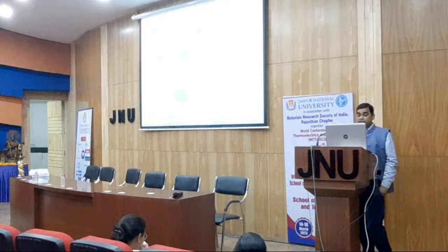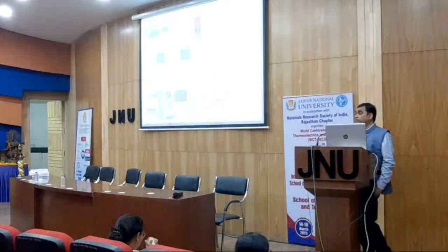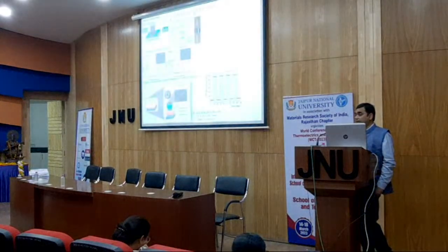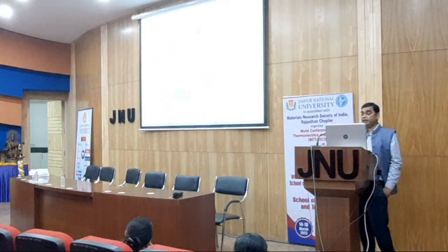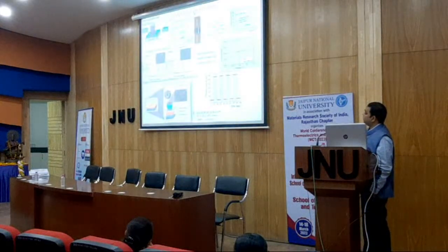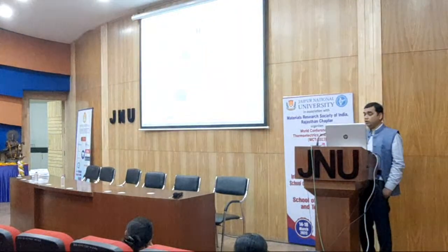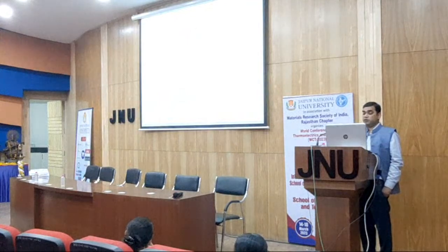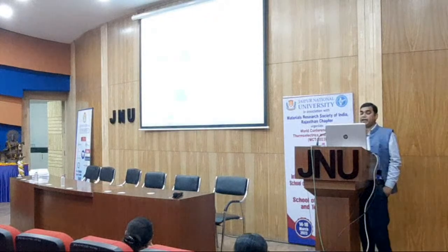And if you see carefully, the commercial silicon-based device is having 0.1 ampere per watt. Here we are talking about 10 ampere per watt responsivity at 1 volt bias. And in fact, this device is also able to give a very good response even with no applied bias, with responsivity of 132 milliampere per watt with a dark current as low as 95 nanoampere.